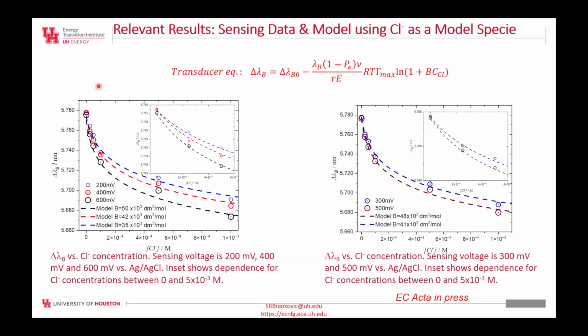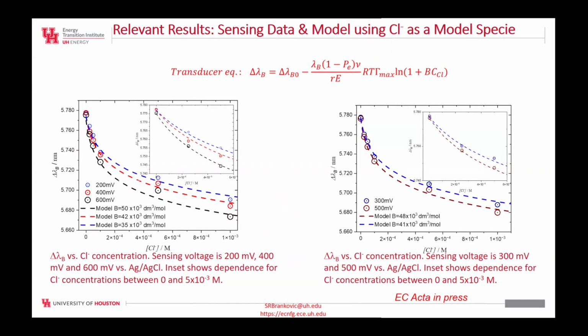And to give you an idea how well this works, let me demonstrate using data where we test the sensor performance, where instead of hydrogen we have a chloride ion in the solution going from 10 to the minus 6 molar concentration all the way to 10 to the minus 3. You can see the sensor performance and the transducer equation model. The sensor is capable of detecting high or low concentrations, and it's operational in different environments. In this particular case, we made the sensor electrochemical, so we can change the potential on this fiber because this is in solution. But for the gas phase, it's going to be even simpler.